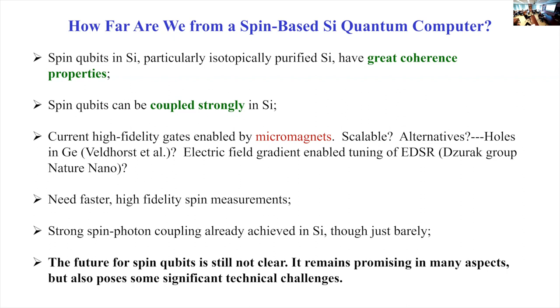The truth is, disorder itself is not too big of a deal if it is static. Mostly, from a decoherence perspective, it's a question of whether a defect has dynamics. If it has dynamics, then you always face that issue. So I think right now, a lot of the dynamics of defects come from the surface, where you have insulator with metal gates, and that's where defects would often come in, no matter which type of samples you have. And people do believe that might be the main reason for the electrically induced noise.